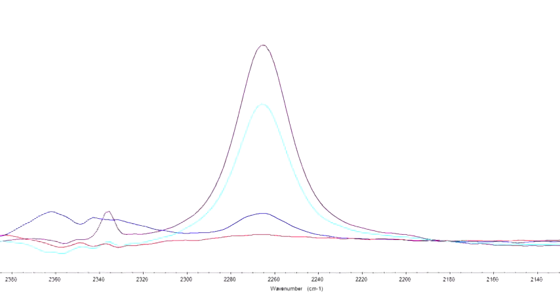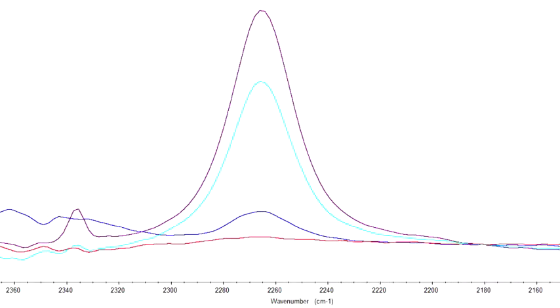This band indicates the degree of excess isocyanate monomer remaining in the system after the reaction is complete and may be used to determine that the proper monomer ratio is found in the formulation.